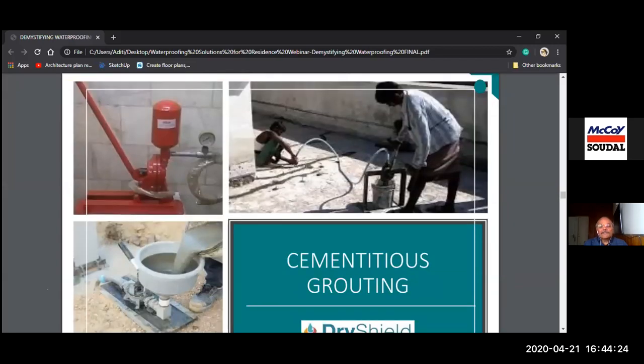So the first grouting system, which is the basic grouting, is cementitious grouting. On the left side, on top is a grouting pump. It's a manual grouting pump, which is used to grout cement slurries. Now, there are two types of cementitious grouting systems. One is where it's done in situ, when you have cement at the site and the waterproofer gets a packet of admixture, which is non-shrink expandable grout compound powder, which is mixed with the cement, and then its slurry is made by adding water, and it's pumped into the concrete.